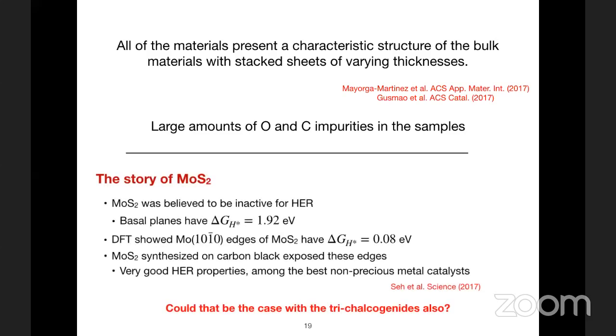But when we looked at this possibility of edges being there, we also around the same time figured out the story of MoS2 from literature. For many years, MoS2 was believed to be inactive for the hydrogen evolution reaction because the delta GH on the basal planes was found to be quite large. But DFT later, motivated by some observations on enzymes, showed that 101 edges exposing molybdenum have very small delta G, almost close to 0. Subsequently, MoS2 was synthesized on black carbon, which exposes these edges, and they were found to be some of the best HER catalysts apart from platinum. So could that be the story with trichalcogenides also?